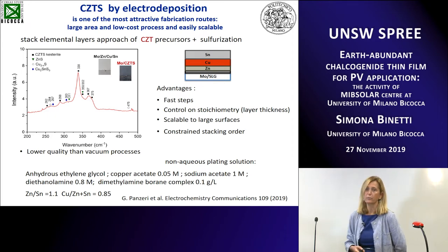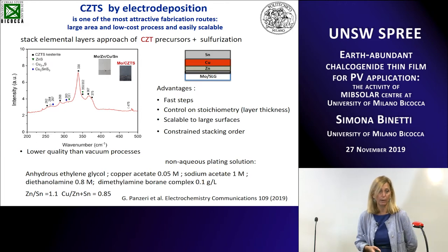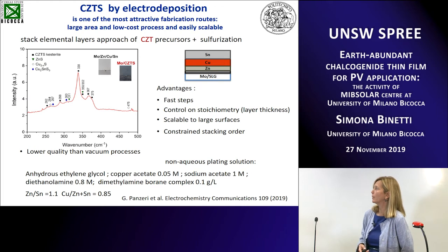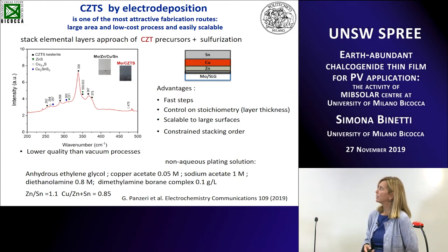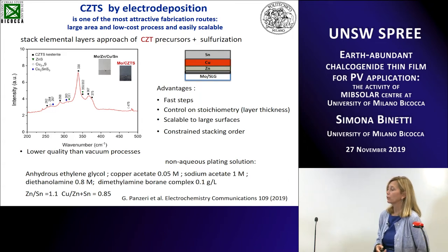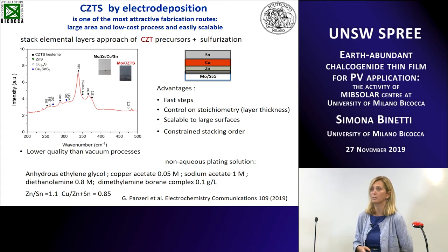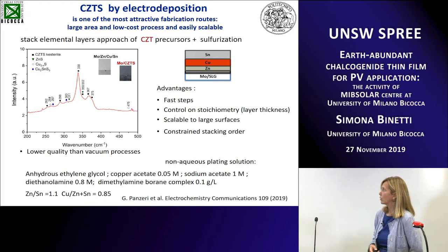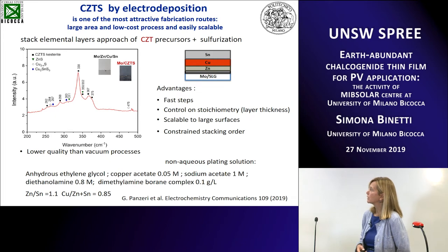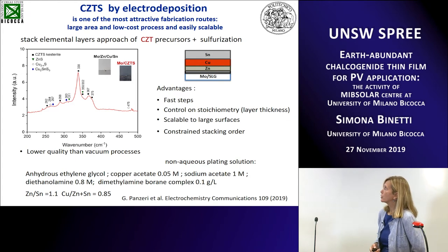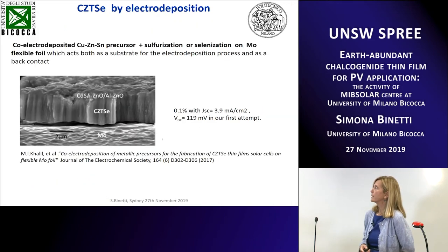At the moment, the quality of the Kesterite that we checked by Raman and photoluminescence is lower than the one that we have with the wet process and with sputtering plus annealing. But the stacked elemental layers approach is a very interesting approach to make Kesterite films, because in these steps you can control the stoichiometry quite well, changing the thickness of the single layers and also the order. They are working on different types of solution. This is one that has been recently published, a non-aqueous plating solution. We also checked the possibility of making CZTSe by electrodeposition, and this is our first attempt.